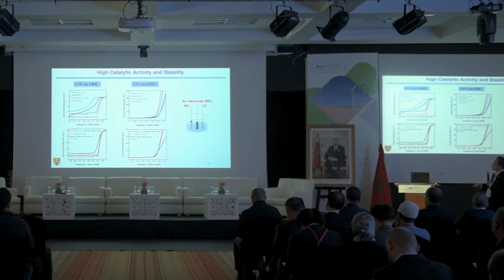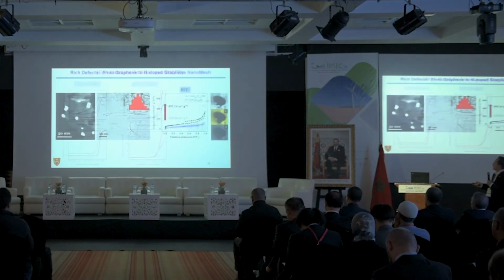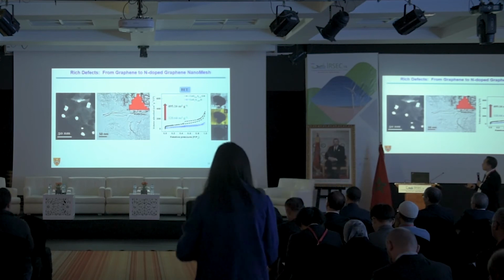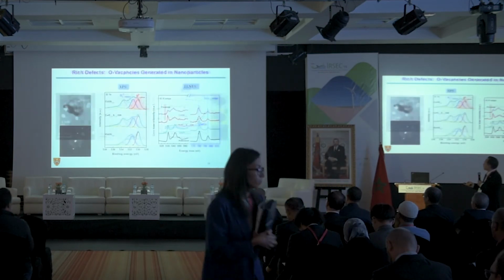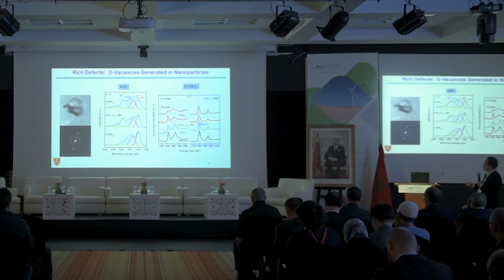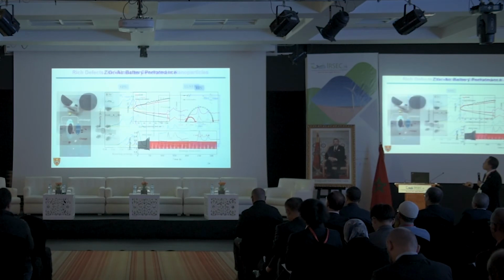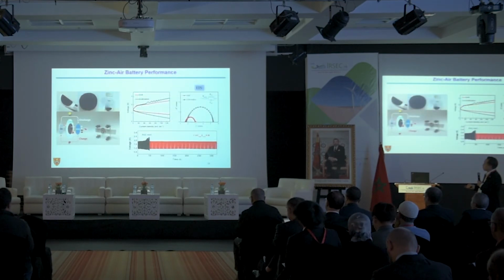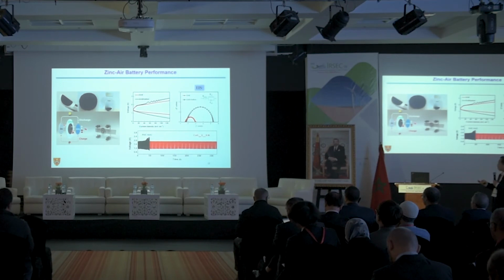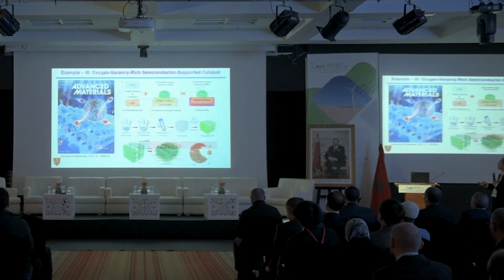If you take a look, this is a half cell, right? The onset potential is good, and this is the OER, also half cell. If you take a look at the SEM, you can see the pores were created and a lot of defects exist, proved by the XPS and the ELNES. We also checked it in the zinc battery cell, and you can see this type of non-precious bifunctional catalyst is also very stable, and the resistance is pretty small. And that is only the catalyst itself.